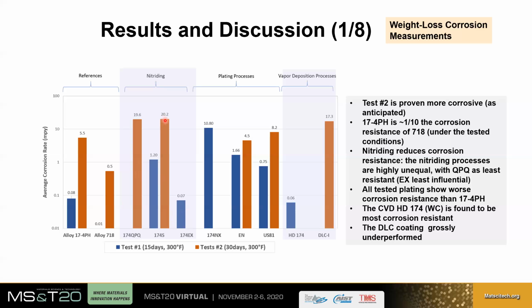On the contrary. The same can be said of the plating processes we've selected for this investigation. We can see that the corrosion rates are pretty significant and essentially always higher than what you see here for the reference alloy. So definitely there is no improvement in applying any of these electroless nickel processes, or even this very advanced process here, which happens to corrode as well.